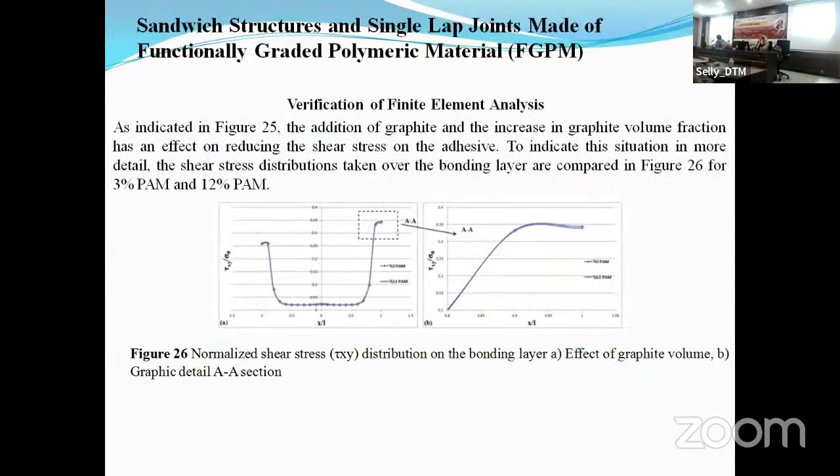In that figure, increasing the graphite volume fraction is effective in reducing the shear stress on the adhesive. We can say, yes, our model is true, and our model is verified on the basis of the analytical model. Okay. I need a break.